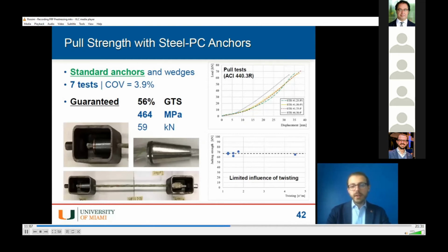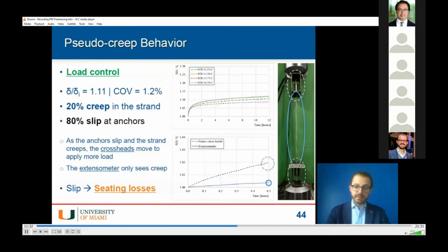You see from the diagram on the right that even though we are dealing with a prototype material, we are treating it in a pretty bad way because we are coupling it with bare steel. We are getting quite consistent behavior at 56% of the guaranteed tensile strength of our raw material itself. And this is a level that can allow us to achieve effective pre-stressing. But we don't just need our material to be pulled, we need it to maintain its pull for quite some time while we pour our concrete. We wait for it to harden, and then we can release it, because remember, we're dealing with pre-tensioning right now.